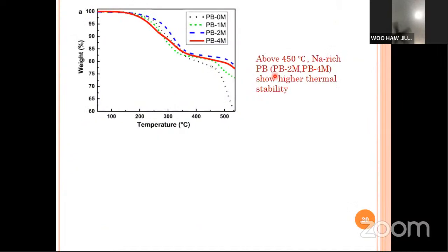This is what we obtained for TGA. If we compare to the earlier Prussian blue, again, we have less than 5% water content. Then after that, we observe that for the 2M and 4M Prussian blue, it shows higher thermal stability.